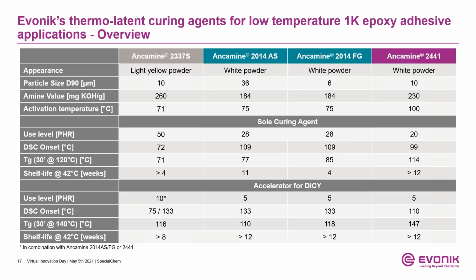Coming now to the modified aliphatic amines in more detail, the comparison chart shown here is meant to give you a brief overview of the properties of the products themselves and the potential when used as a sole curing agent or as accelerator for dicyandiamide. All the products are micronized powder type products, which can be easily dispersed into your epoxy adhesive formulation. A brief note at this point, the main difference between Ancamine 2014 AS and the FG grade is just the particle size, which basically leads to the differences in curing and shelf life properties shown here.